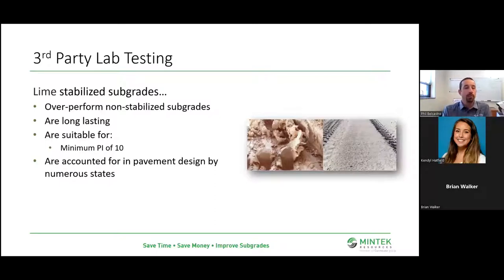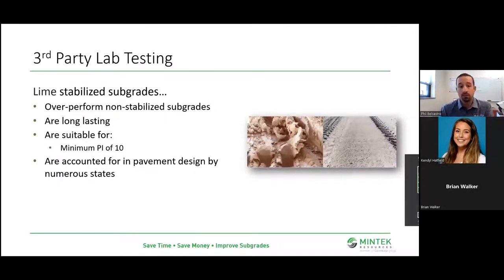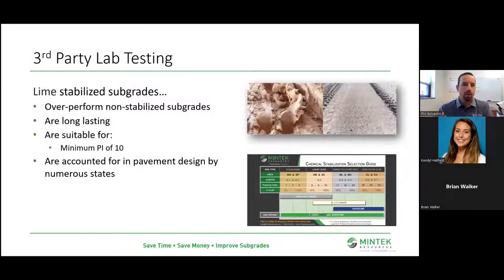They concluded that lime stabilized subgrades overperform non-stabilized subgrades. We're gonna see some numbers coming up in the next slide. They're long lasting. Basically, you get the stabilization, you get those pozzolanic properties. It's not liable to leach or lose its strength. They're suitable for a minimum PI of 10. So that's something we've highlighted on our chemical stabilization selection guide. You can see between the white box and the blue bar, that we're talking about those same PI levels, minimum PI of 10, and that they're accounted for in pavement design by numerous states.